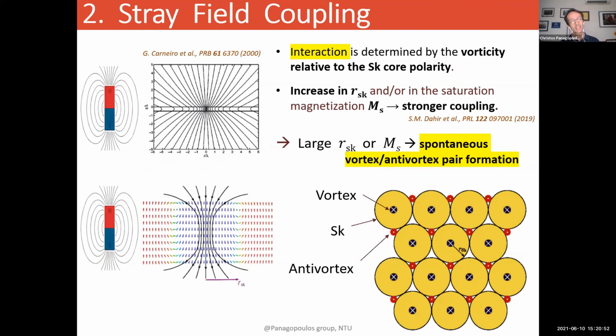Now, the second coupling mechanism is stray field coupling. Here, the interaction is determined by the vorticity relative to the skyrmion core polarity. So if you increase the radius of your magnetic skyrmion or your magnetic vortex, and the saturation magnetization MS, that would give rise to a stronger coupling. So a larger skyrmion, a larger magnetic vortex, or a higher saturation magnetization in your magnet would give rise to a spontaneous vortex or anti-vortex pair formation.